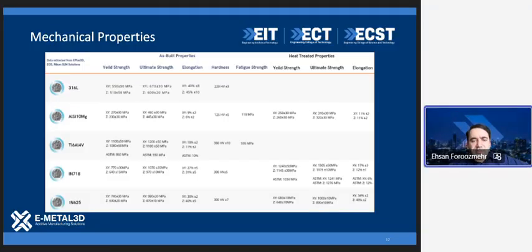This table, which is quite small for myself, I hope you have it larger, shows the properties for some of the typical alloys, like stainless steel 316. This stainless steel is widely used in industry. Just to know, the yield strength of round bar of 316 in the market is about 220, 230 megapascal. And as you can see here, it is 500 plus yield strength. So we are expecting double the strength when you 3D print that material. So we are not talking about missing properties or lowering the standards, but also about raising the standards of the strength we expect.